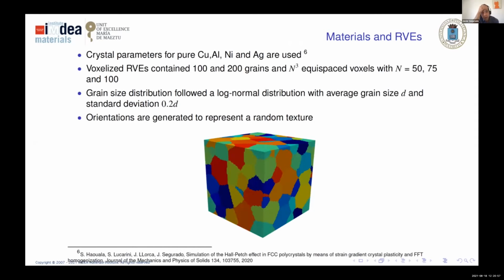We're going to use 4 alloys: copper, aluminum, nickel, and silver, and we're going to use RVEs with 100, 200 grains and different discretizations. The model is not cheap, so we normally use 100, which is enough. We're going to create a synthetic RVE with an average grain size and standard deviation following a log-normal distribution, and for this example we use just a random texture. The model has some input parameters obtained from DD, in the case of dislocation interaction, or from experimental studies, but we have not fit any parameter. That's precisely the reason why we want to minimize the number of parameters of the model.